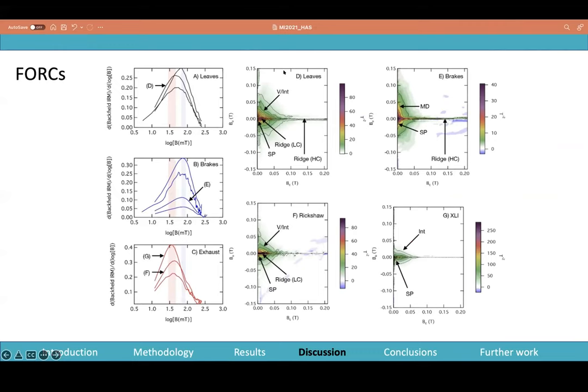You can see how the FORCs in particular are very useful in differentiating these fingerprints, these different sources. You can see how our leaves, in these backfield remanent coercivity distributions, lie somewhere in between our brake pad residue dust samples and exhaust dust samples, and how the leaves have both a high coercivity ridge and a low coercivity ridge component, which gives us a ballpark idea that it is a combination of this MD brake signal plus something which is coming from the exhausts. But the magnetic granulometry results just showed our brakes to be in the MD region and failed to recognize something which might be more related to this single domain like structure over there.